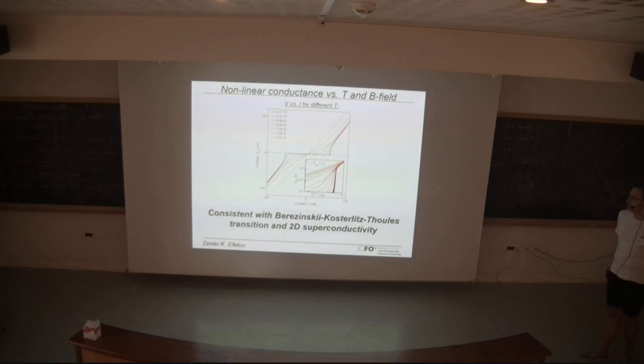Then, of course, we can perform nonlinear conductance measurements, so we can look at the IV characteristics of this state. And indeed, we really observe a zero resistance state here, where by changing the current, we don't change the voltage drop across the sample. And then at a certain critical current, this state becomes resistive again. And this looks very much like what you expect from IV characteristics of a superconductor, where one can show that something like an IC exists.